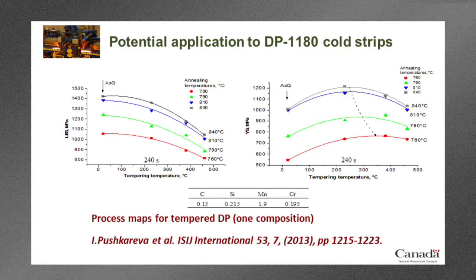Now the 760 was the steel that I showed you in the previous slide, and it had 38% of ferrite phase in it. As we increase the intercritical annealing temperature, the amount of ferrite will decrease until at this 840 degrees C point, we have virtually no ferrite left. It's like 99% martensite.